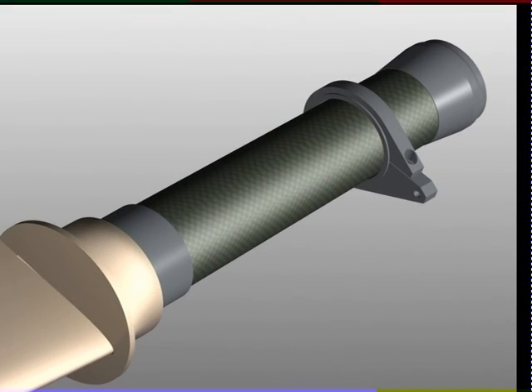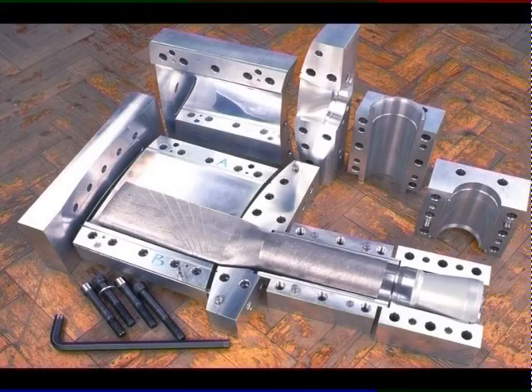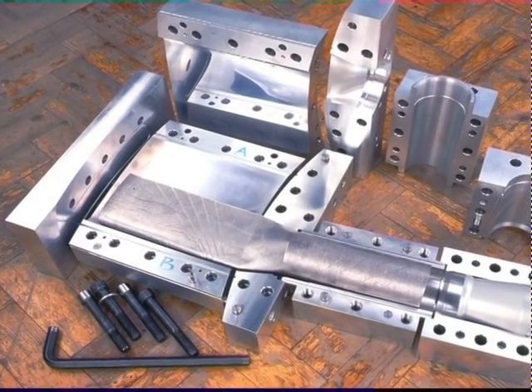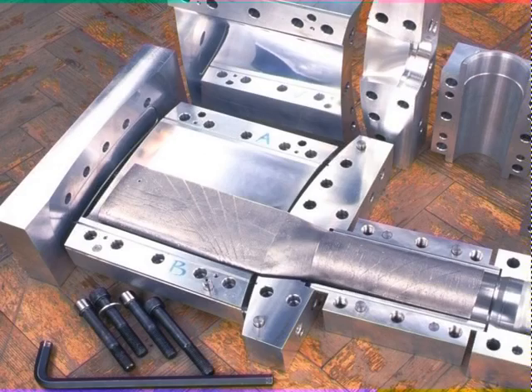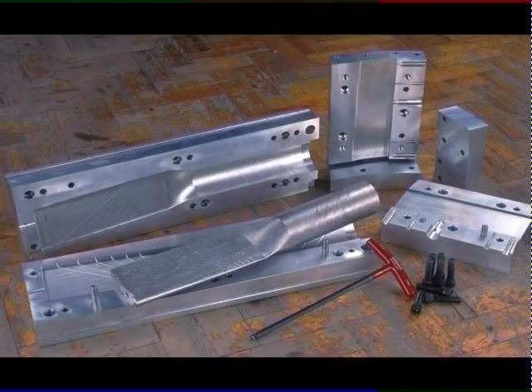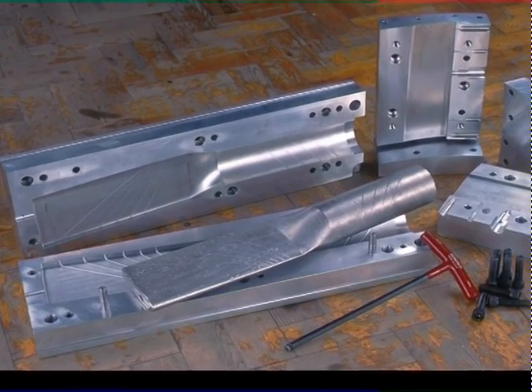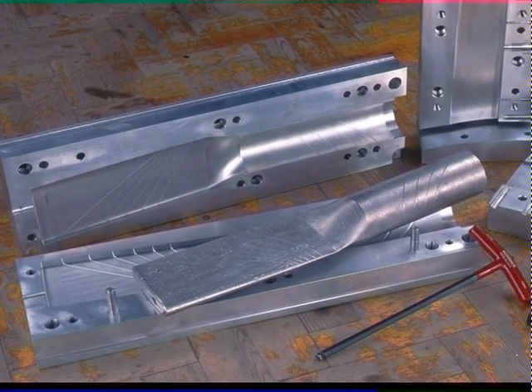The blade and spar will be a single piece, hollow, carbon-epoxy composite, bonded to an aluminium alloy attachment ring. In a modified resin transfer moulding process, the various layers of carbon cloth will be kept in place by cast metal cores, made of very low melting point alloy. The cores will melt out during the curing cycle to leave lightweight components.